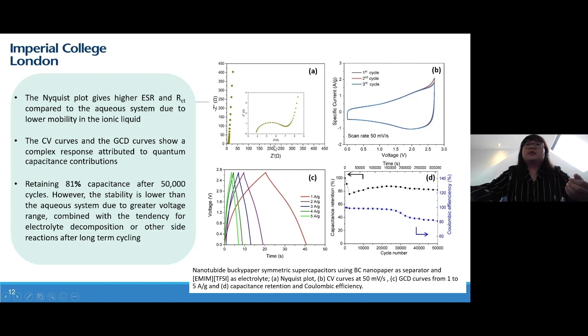But providing around 3 ohms in ESR, the RCT is still low for an ionic liquid system, which shows the nanotube bucky paper is very good in terms of conductivity. The CV curve shows a butterfly shape here, which is not similar to the aqueous system, due to the quantum capacitance contribution from the nature of single wall carbon nanotubes interacting in the ionic liquids. It is also shown in the galvanostatic charge discharge curve, which is not a perfectly triangular shape